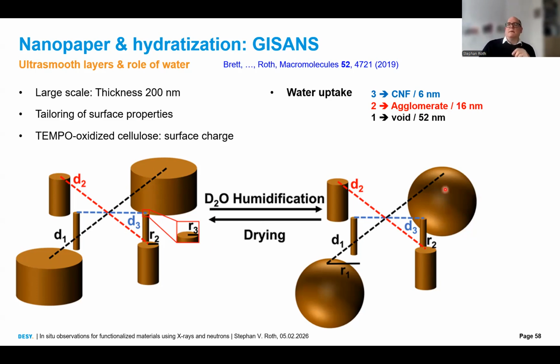What is this? When you look at the water uptake, relative humidity 90%, this large structure has a spherical appearance. So you have D2O and you have a spherical appearance. So this is a water droplet. This means in my cellulose nanostructure, I have water droplets. Where can they occur? In the voids. So we detect here spherical voids in our cellulose nanofibril template.